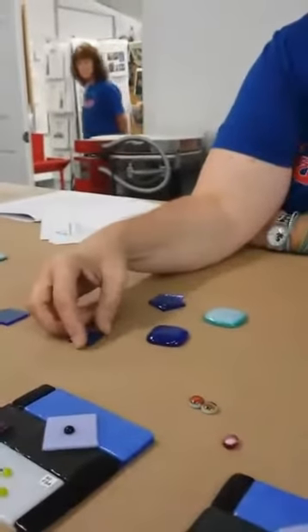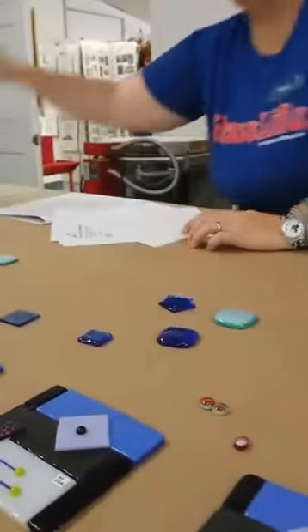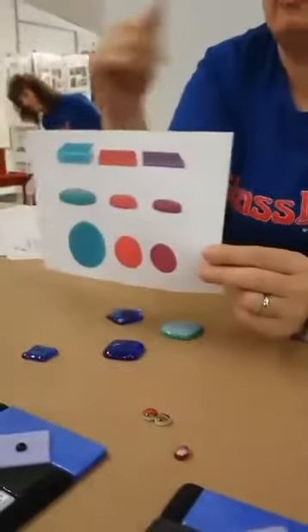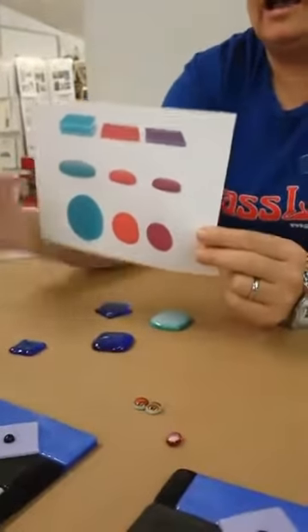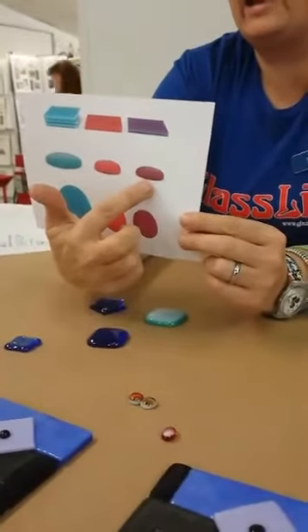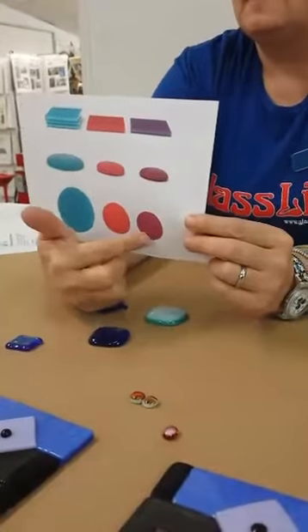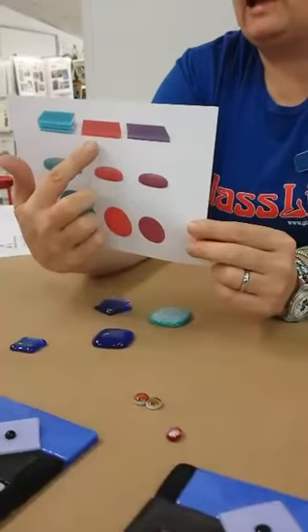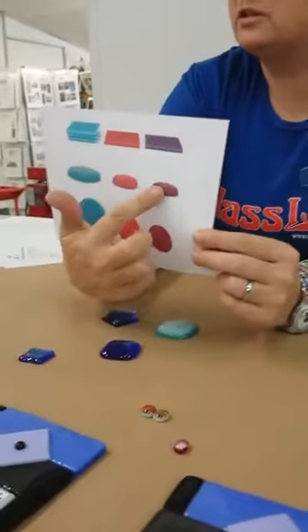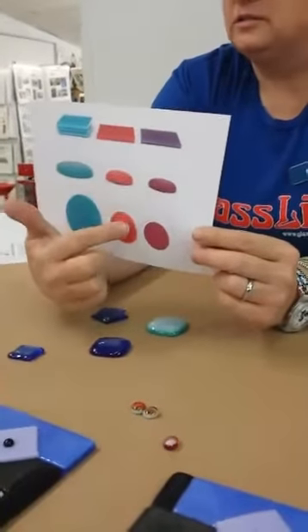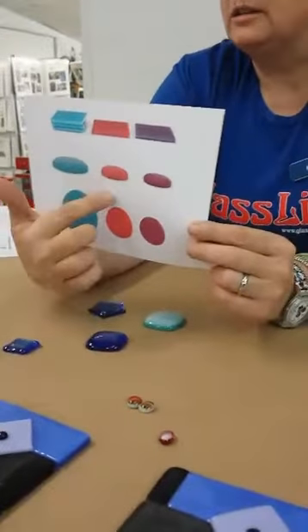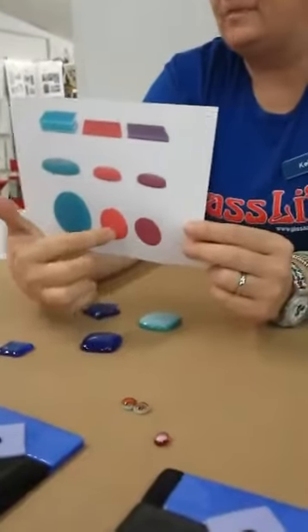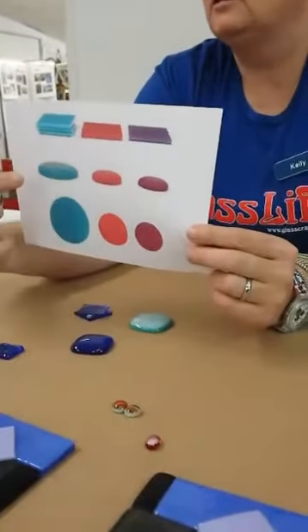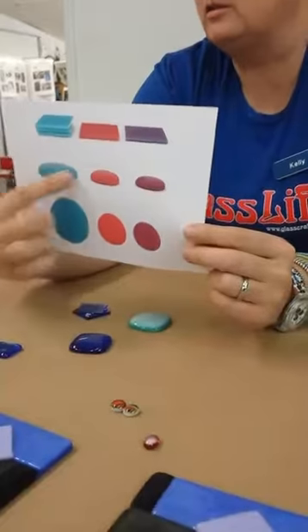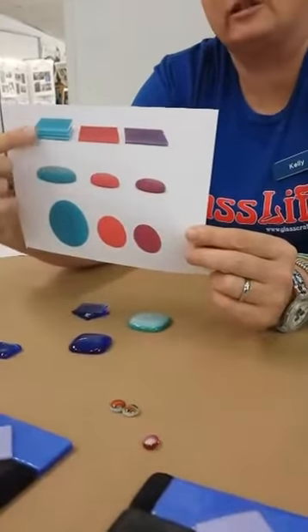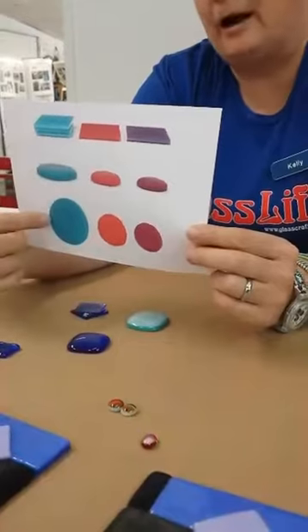And you've probably seen an image like this one that talks about I have one piece of glass, I have fired it, it's gotten 1/4 inch thick, and the size hasn't changed a whole lot. I have 2 pieces of glass, I fired them, they're still 1/4 inch thick. It shrunk a little here, stayed pretty much the same size here. I have 3 pieces of glass, I fired it, it's still 1/4 inch thick. Well, that glass had to go somewhere because it's more than 1/4 inch here, so it's spread out.